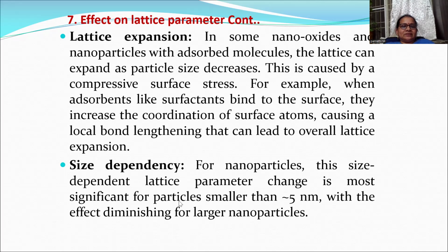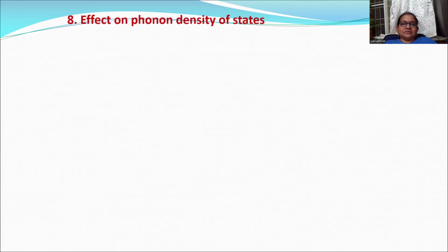Similarly, the third one, that is size dependency. For nanoparticles, the size dependent lattice parameter change is most significant for particles smaller than 5 nanometer, with the effect diminishing for larger nanoparticles. So these three parameters are to be considered under lattice surface expansion.